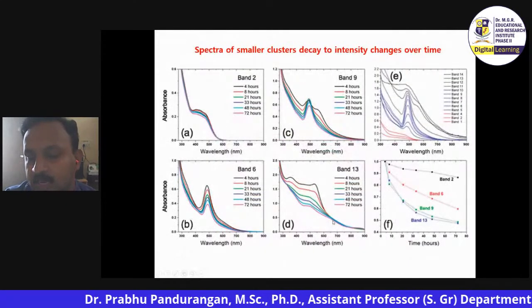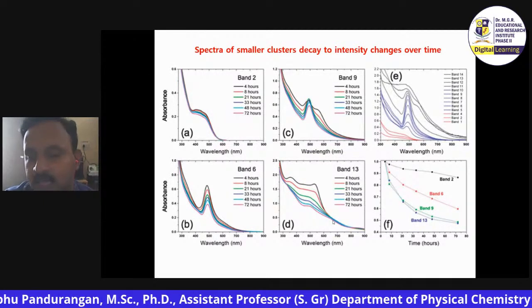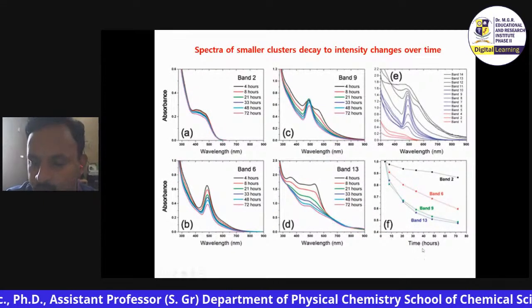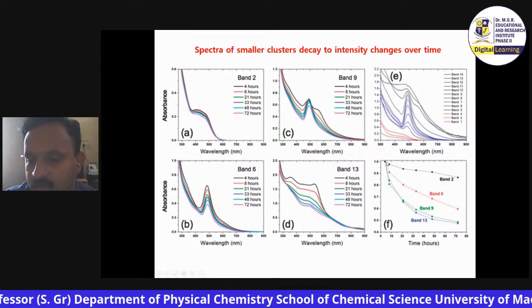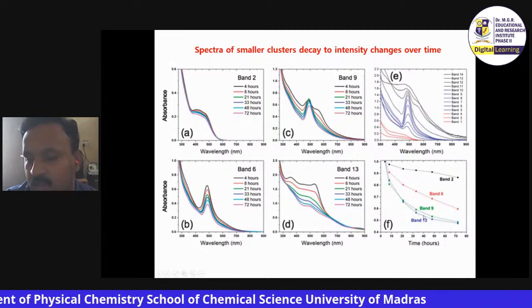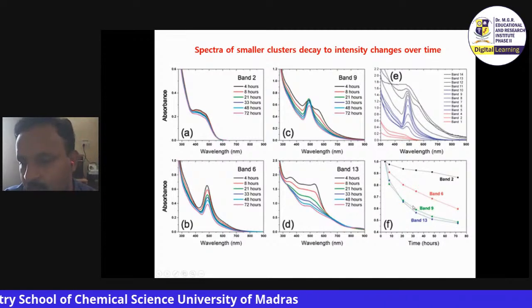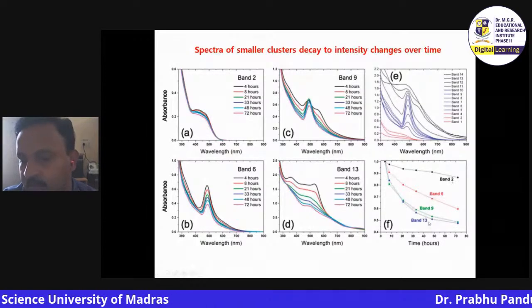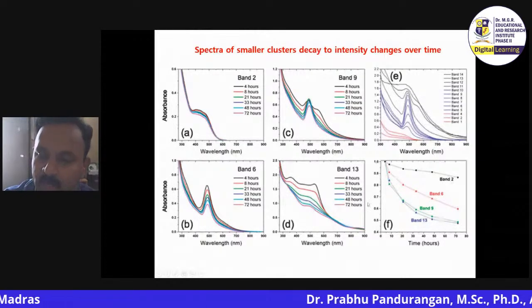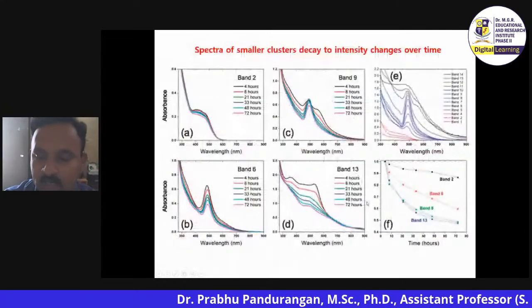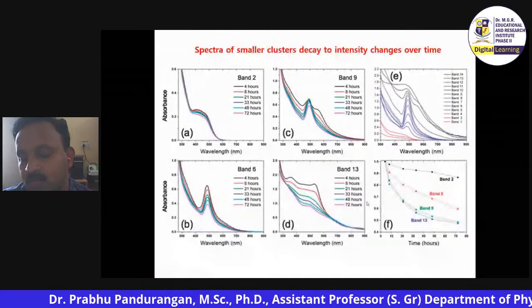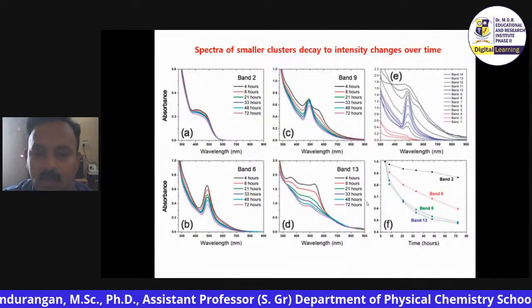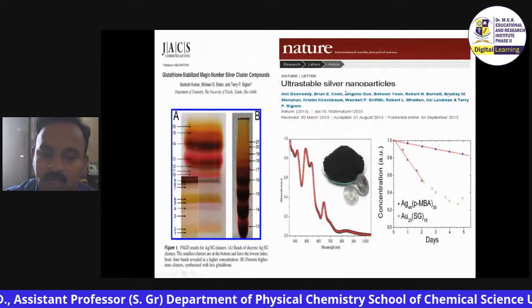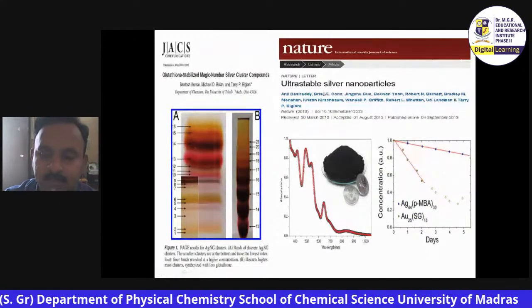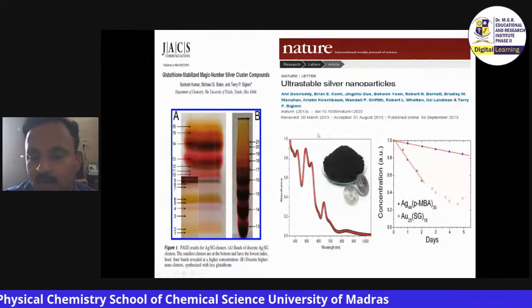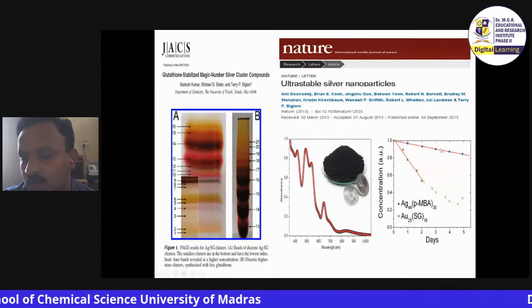So there is a complete quantum confinement effect where size matters, and you can see over a period of time the absorption stability. As you increase the time, the band stability can be arrived at from this. Band 2 seems to be highly stable as compared to band 13. Clusters, many people are worried to work with because of their stability. So you can achieve stability with the help of an appropriate capping and stabilizing agent. And now this paper is published, I said this paper was published in Nature in 2013, and this is the UV-visible pattern of that silver 44, and you can see this plot. Gold 25.